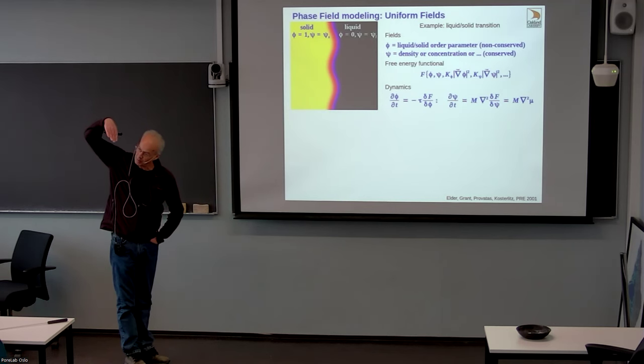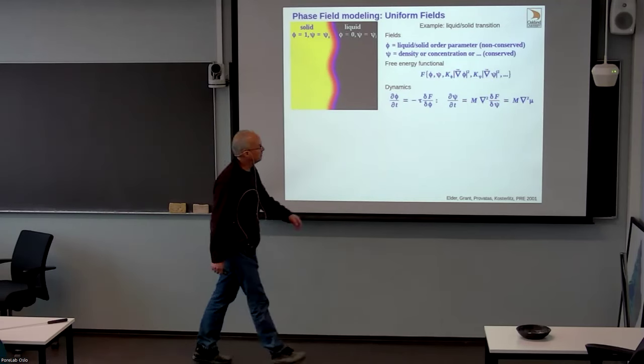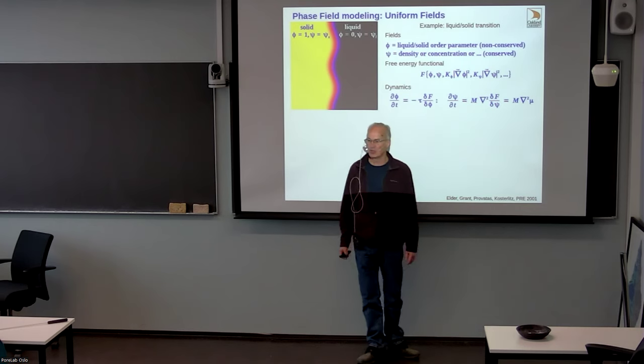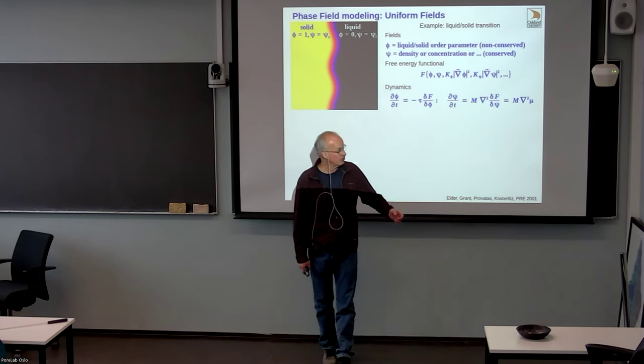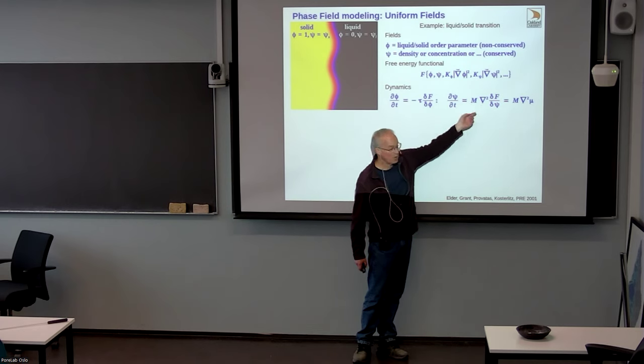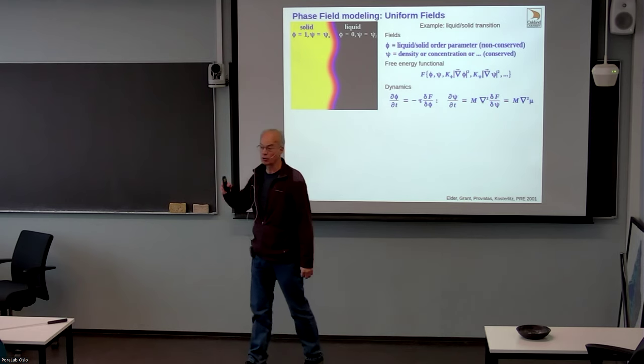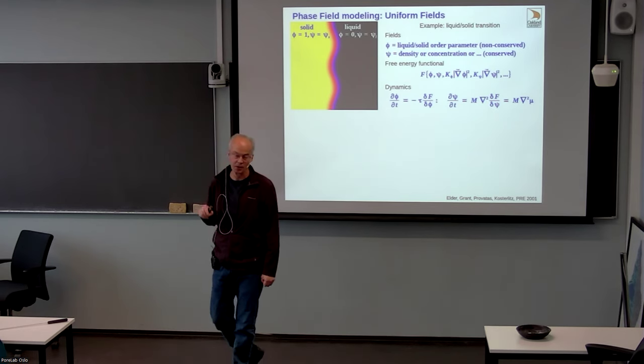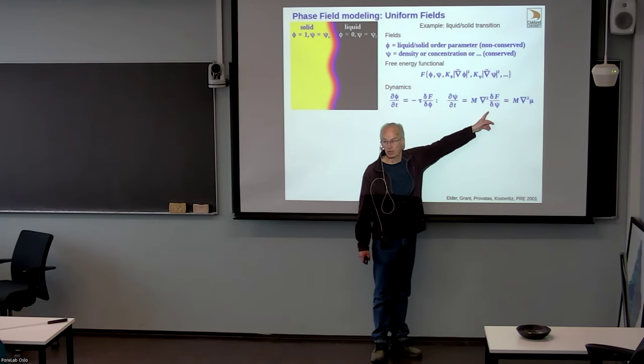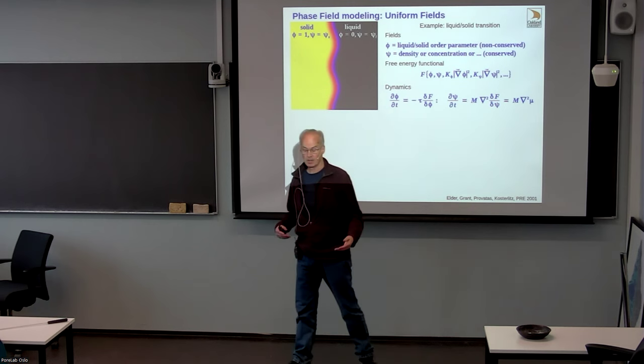You're typically set up to relax toward the minimum energy state. You have to be careful with conserved fields. This goes back to Cahn, who said the rate of change is proportional to the gradient of a flux, and the flux is proportional to a gradient in the chemical potential. If this were a number density, this quantity would be the chemical potential. So the dynamics are really driven by gradients in the chemical potential.